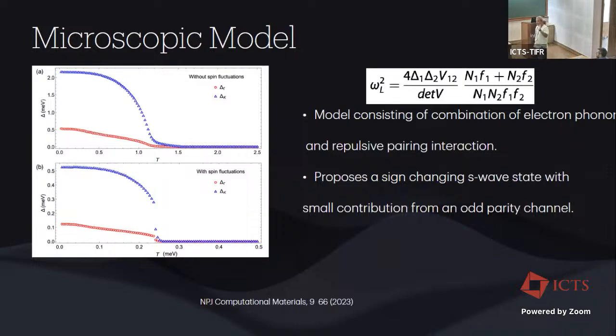So what they did was they considered the electron-phonon interaction, which they extracted from first principles calculations, as the pairing mechanism, and a repulsive spin fluctuation mechanism, which they took from an average Stoner. So it was momentum independent, a constant repulsive interaction. And from there, they essentially showed that you get a gap like this. And then they argued that you don't necessarily need a singlet-triplet mixing to understand the formation of these Leggett modes, but the strong anisotropy between the gamma-centered pocket and the K-centered pocket can also lead to an effective free energy approach that can give you modes or in-gap states which are less than delta. Okay, but the question was that they necessarily needed a gap on the gamma-centered pocket, which was much smaller.